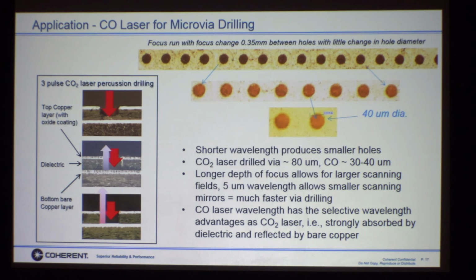Now the copper is 100% reflective at CO2 laser light, and by the way at CO, okay? And this is important for the application because then finally the cleanup pulse goes down, and even if you hit it with a lot of light, you'll never damage this layer below because it's 100% reflective. And CO laser has the exact same characteristics.